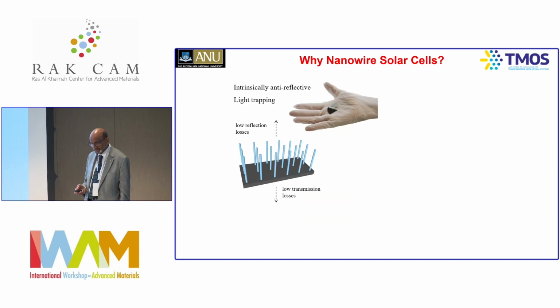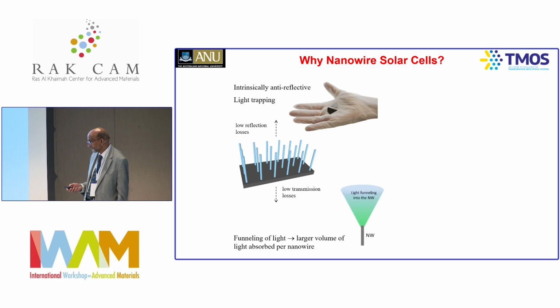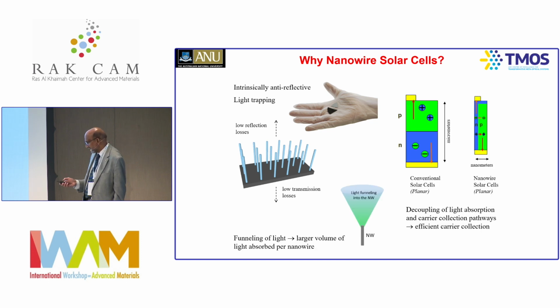Now let me move towards solar cells. It turns out that nanowires have a lot of positives in terms of solar cells. Typically, when you make a thin film solar cell, you make it thick enough to absorb all the sunlight, and then carriers need to migrate long distances. But in the process, you end up losing some of them to impurities, defects, and surfaces. But if you make a nanowire, you can make it as long as you want to absorb all the sunlight, and you make a PN junction in the radial direction. That means carriers can be collected very efficiently. You're decoupling the light absorption pathway and the carrier collection pathway. Also, nanowires can act like light funnels because of their high refractive index, which collects the light very efficiently. Also, they have low reflection losses.